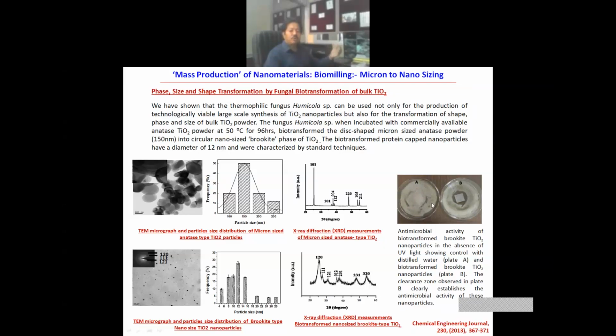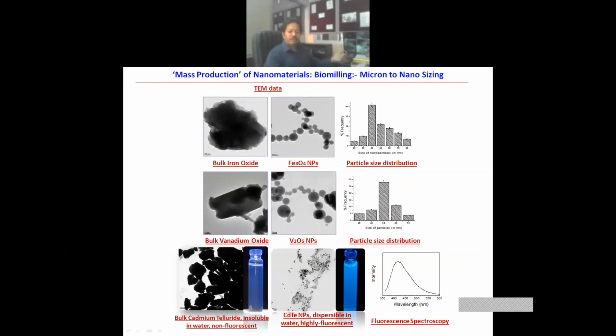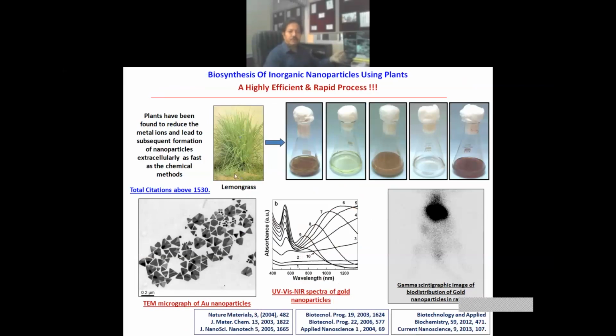Now, how will you separate these nanoparticles? This is a major issue. We are working in that direction also. Now, another mushroom. You see, this mushroom converted the gold into gold nanoparticle and silver nitrate into silver nanoparticle. Similarly, from Ganoderma, again we synthesized silver and gold nanoparticle. Here we are getting different shape and size of the nanoparticle. Chemically, physically, very, very difficult.